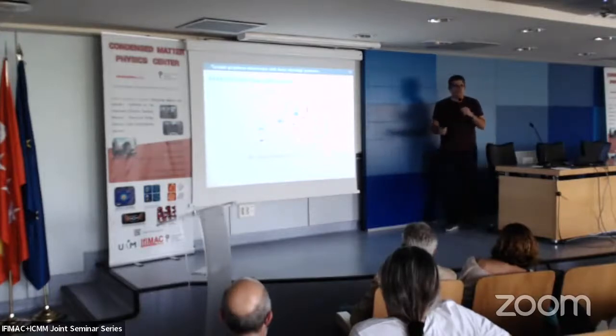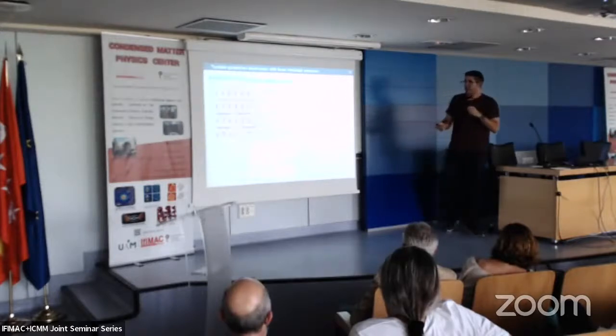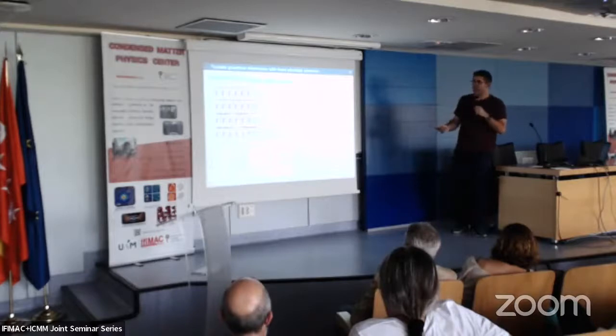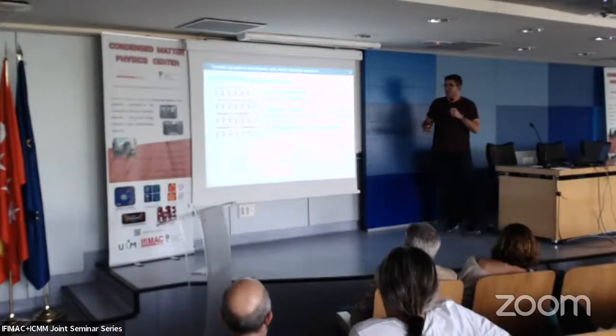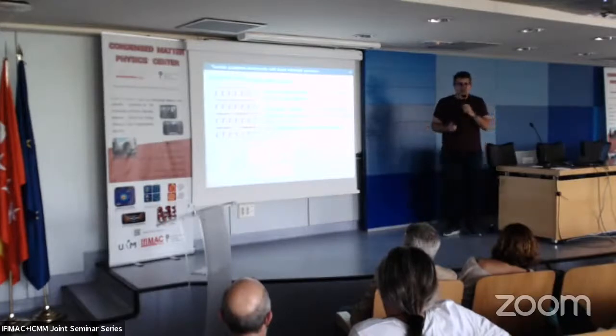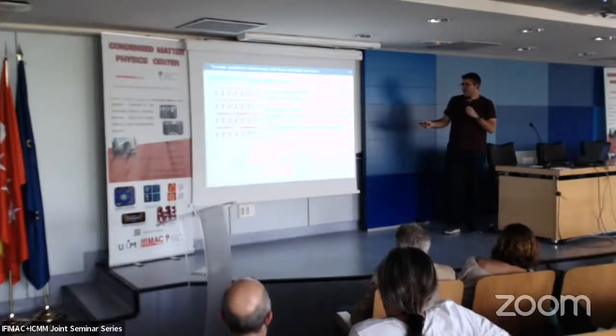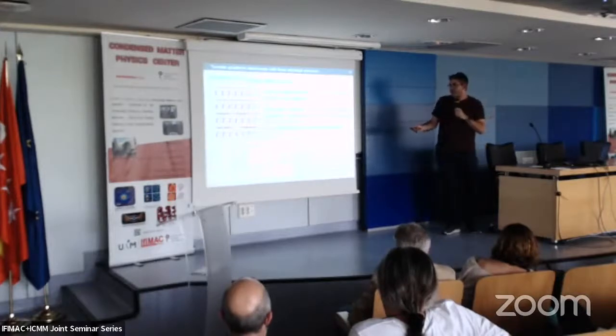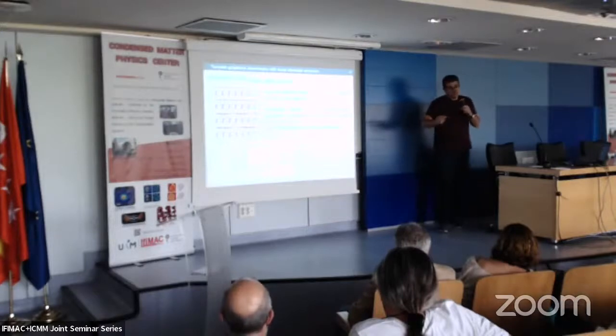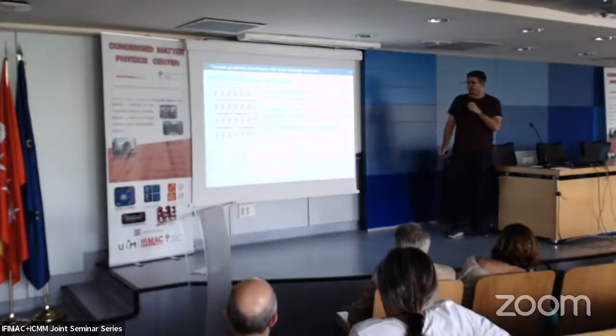We saw this effect of the doping, but why was this really happening? Here is where DFT calculations come in, and the group of Fernando did some simulations in which we put graphene on top of different configurations of silicon dioxide, mimicking the possible states we have. By doing so, what we found is that if there is just van der Waals attraction between the graphene and the substrate, there will be no charge transfer, there will be no extra doping. They found that some chemical bonds were needed, even if there is a very low fraction of bonds, to have this charge transfer that will give the graphene a Fermi level shift of the order of 0.3 electron volts, which is compatible with what we observe experimentally.